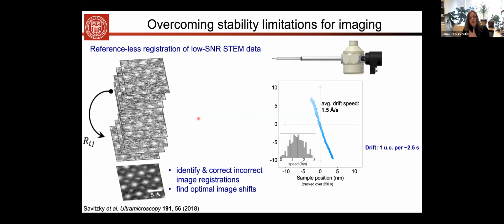So how, for imaging, have we overcome this limitation? The way we are doing it is similar to what is done in biology, which is you record basically movies of your image or of your region of interest. And what we then do is we set up a registration method that is optimized for extremely low or low signal to noise data. And that allows us to get to the signal to noise ratio that is needed for highly precise measurements of the atomic crystal.